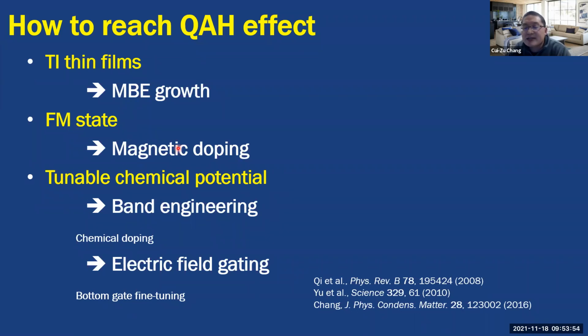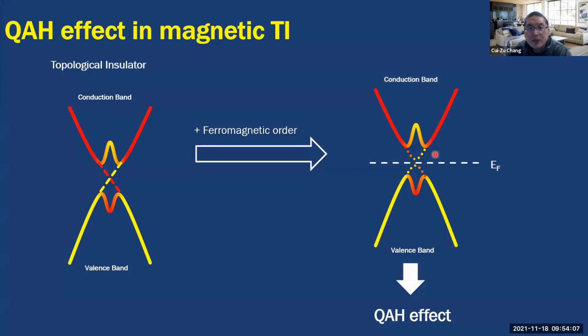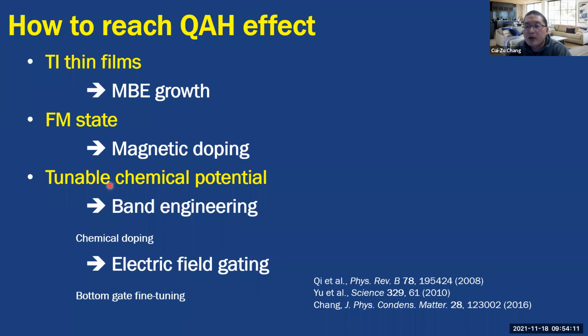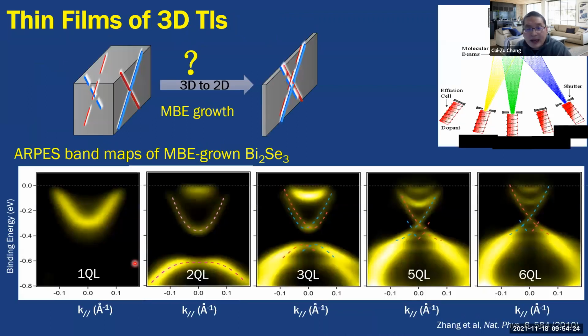We use the approach from diluted magnetic semiconductors: we use the magnetic doping effect in the topological insulator to realize ferromagnetic order. And the third condition is that we need to tune the chemical potential into this small gap, that is, into the insulating regime. We use 2 methods: one is chemical doping, and the other is the gating effect.